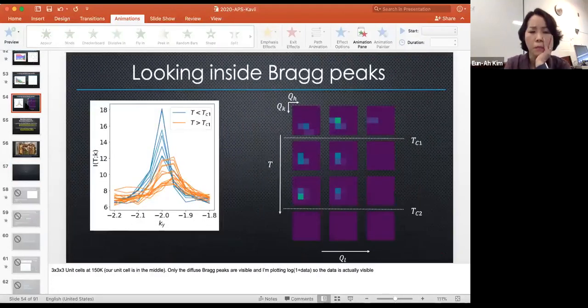So there is a crystallography which is looking for the position of atoms that's going by crystal symmetry, and then there is a whole process of reduction. What we are looking at is less of crystal structure, although we are looking at the structural distortion. But the first thing we looked for was, can we quickly find charge density wave, for instance, or some ordering phenomena. And to look for that, the conventional way of doing it is, because it's hard to visualize 3D intensity distribution, and there has been no better way than to just visualize. Human researcher looks at it, and that's why I said it takes many months.